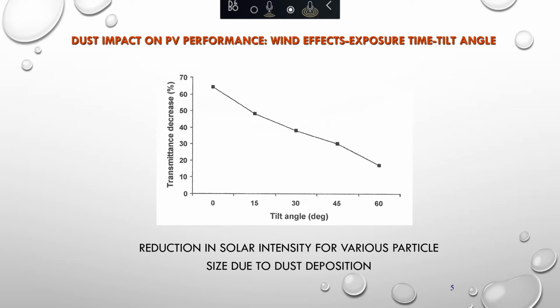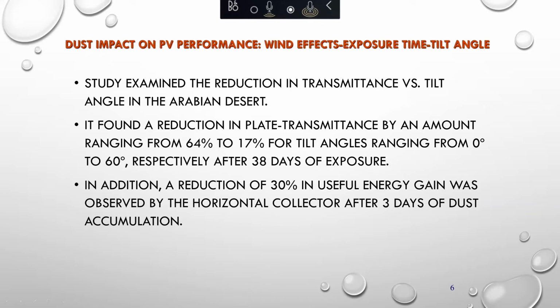findings here. This study examined the reduction of transmittance versus tilt angle in the Arabian Desert. They found that the more you increase the tilt angle, the transmission reduction becomes minimal, which means that at 0 here at the beginning of the spectrum, you have a dead flat module that reduces efficiency by up to 64% for the PV module. And funny thing here, in only 3 days with a 0 tilt, you can get a 30% reduction right away. Again, this is a trade-off between the tilt angle and the dust accumulation.